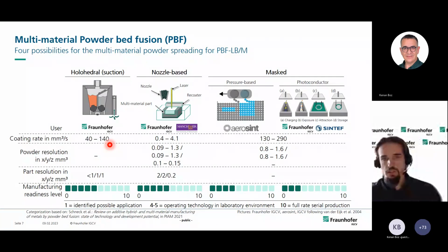Of course, the nozzle-based one, as it's a fine nozzle, as you want to achieve fine contours, is very low. And with the pressure-based mask systems, as you can place your powder all at once per layer, it has the highest coating rates. The resolution, how the powder is placed onto the build plate, is very good for the nozzle, but it's still very good for the masked applications. And the part resolution, I will show you later with our holohedral system, is at the moment very, very good.